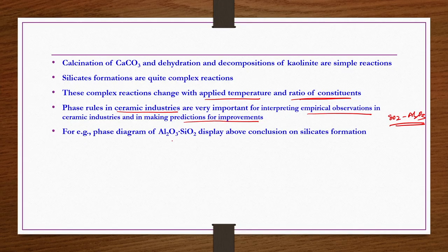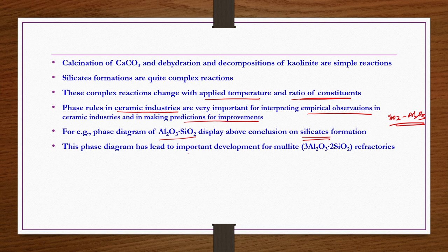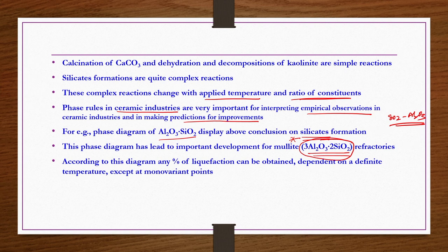For example, the phase diagram of Al2O3 SiO2 displays the above conclusion on silicate formation, that silicate formation is a very complicated reaction. This phase diagram has led to the important development of mullite refractories, right, many of the refractories are mullite type refractories, which have the chemical formula 3 Al2O3 2 SiO2, okay. According to this phase diagram, any percentage of liquefaction can be obtained. If you have pure SiO2 and then Al2O3, then it's a different thing. But if you have a combination of these two, any percentage, 10% to 90%, then you can obtain the liquefaction at a lower temperature itself, right?